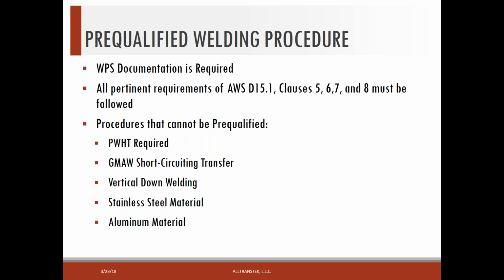Okay, that's pre-qualified welding procedure. This is where we can't just say that I have D15.1 in my bookcase and therefore I have a pre-qualified welding procedure. That's not allowed. We still have to qualify or have documentation for the pre-qualified procedure. And we have to meet all the pertinent requirements of AWS D15.1. That's clauses 5, 6, 7, and 8.